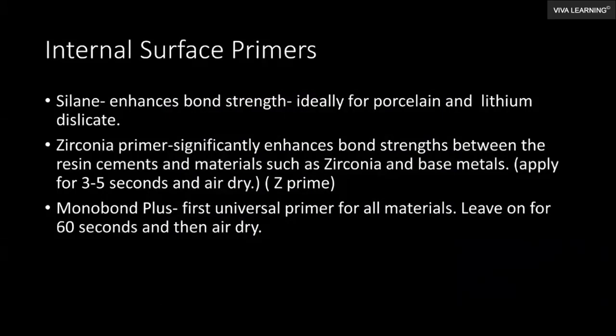In order to get optimal adhesion, we have to treat our substrates in the right way. Otherwise, when we cement these, they're not going to really have optimal adhesion or optimal holding. Whenever we're dealing with any kind of porcelain or ceramic product, we need to use silane to enhance the bond strength. Silane can come as a silane primer or a multi-surface primer like some of the manufacturers have, as well as GC.